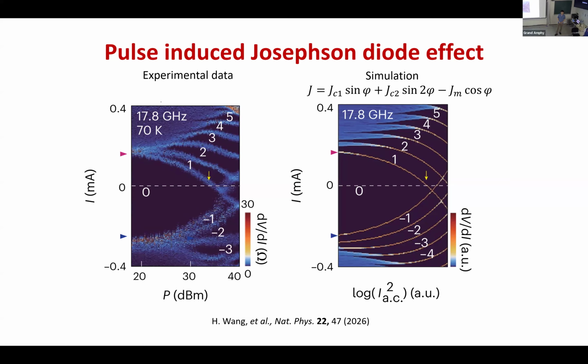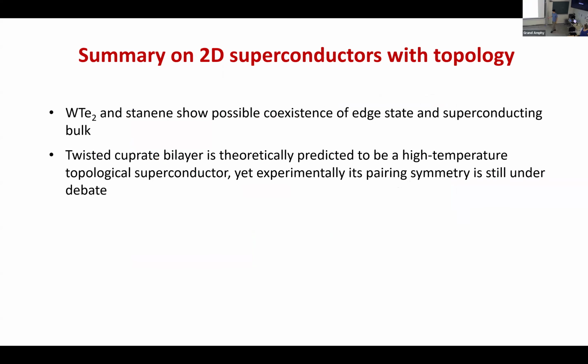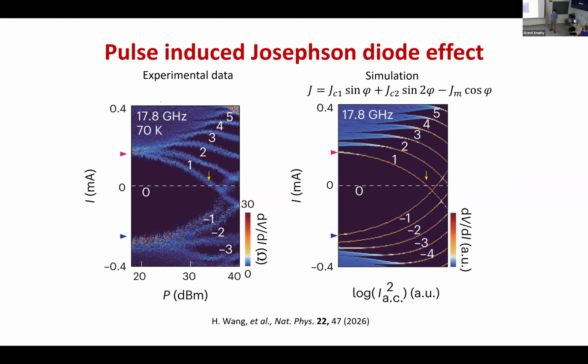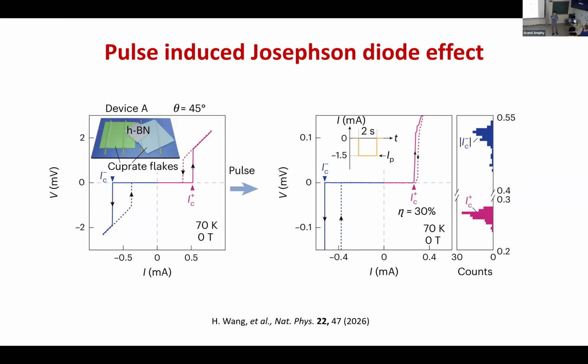There are really few groups who are able to handle Bi2212 to make it monolayer and bilayer. It's an old kind of story with a cryogenic stage, exfoliation. How did you manage to actually make really thin layers to be able to do this twisting? Also, for the twisted cuprates, so far it's not very simple. On each side it has, in our case, minimum 30 nanometers, so 10 unit cells. Okay, so it looks like you don't care so much about the surface. Oh, and then we need to cap it with boron nitride before we take it out.